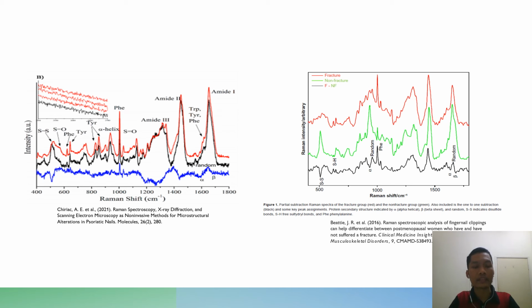For example, in the region of 500 cm-1, there is the presence of disulfide bonds, and it is important to the nail because it is related to the mechanical properties of keratin. And in both studies, it shows that the sample which is healthy and unaffected reaches higher peaks than the one that is affected. Another region that we can see here is around 900 cm-1, where it shows that healthy fingernail has a higher content of alpha helix than the affected sample.